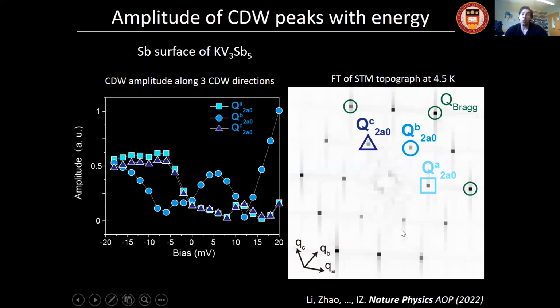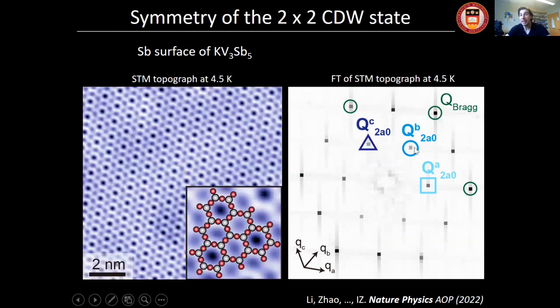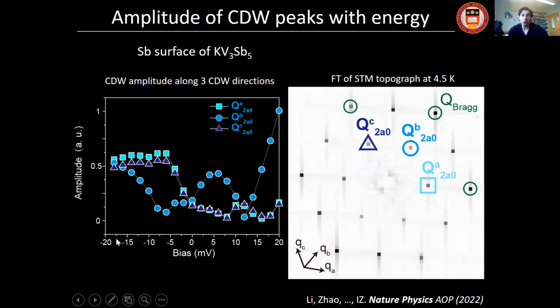The way that we wanted to investigate whether there is any sort of symmetry breaking in this state is to examine the amplitude of these three wave vectors as a function of energy. Here I'm plotting data from a single DOS map from plus to minus 20 millivolts, where we look at the intensity of this single pixel along the three directions and then plot it as a function of energy. So the y-axis is simply the amplitude of the CDW wave vector.